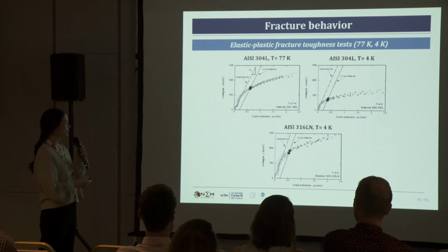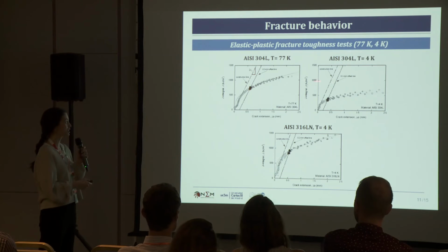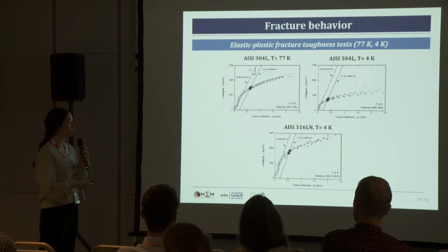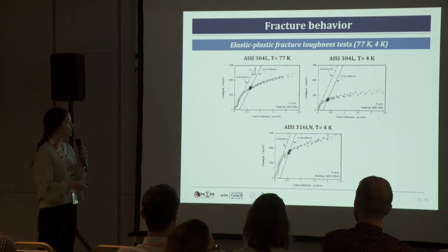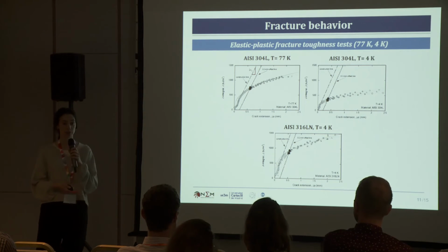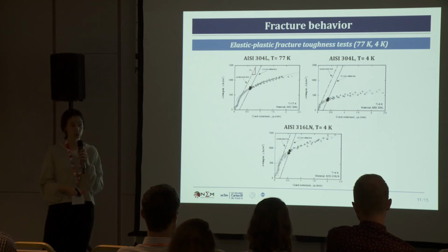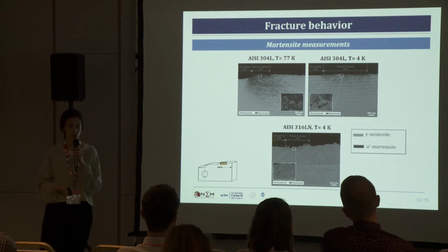For the AISI 304L, what we see is that the fracture toughness is higher at 77 than at 4 Kelvin, and quite high values if you see. And then if we compare at 4 Kelvin, what we see is that the fracture toughness of the AISI 316LN is higher than for the AISI 304L. Let's move now to the martensite content.